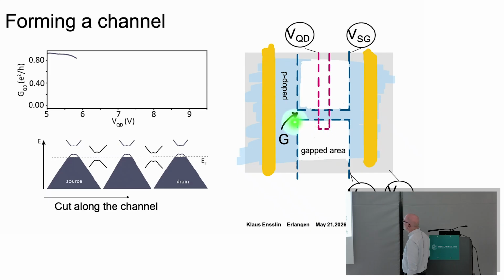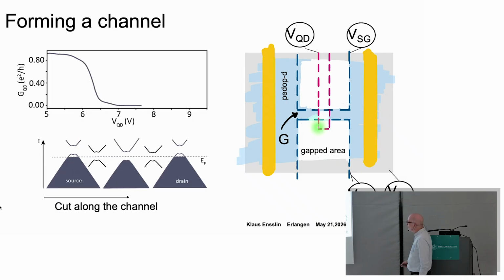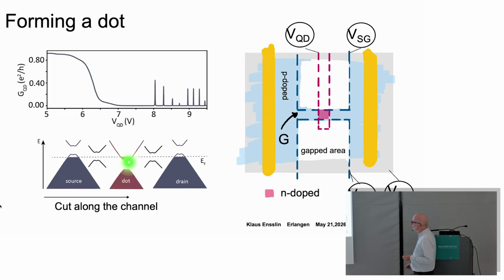So if this finger gate is unbiased, we measure some conductance along the channel, and you see schematically the band structure on the bottom. In this case, we talk about holes. So you see the Fermi level is at the top of the valence band in the source, in the drain, and in the channel. Now we can tune the position of the Fermi level below the red gate, and we can tune it to a regime where it's in the gap. And you see the conductance goes to 0. We have fully depleted the channel, so that's a transistor that you can switch off. And now you keep going, and in the center, you start populating the conduction band. And you see very, very nice Coulomb resonances showing up.